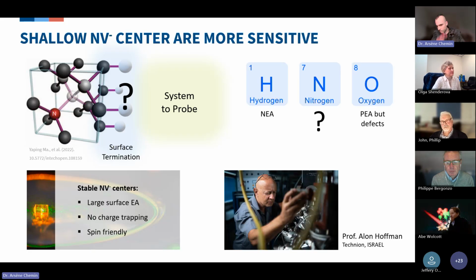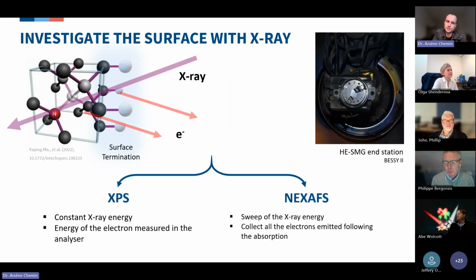And some atoms, the most common one is hydrogen. The problem with hydrogen terminated diamond is that we will get a negative electron affinity of the surface that will tend to pull out electrons, like we won't have any electrons at the surface, so the NV will tend to be positive. Oxygen has a strong positive electron affinity, but it makes a lot of defects at the surface. And so Alon was thinking about using nitrogen for it. And so he developed many different techniques of plasma treatment for the nitrogen surface.